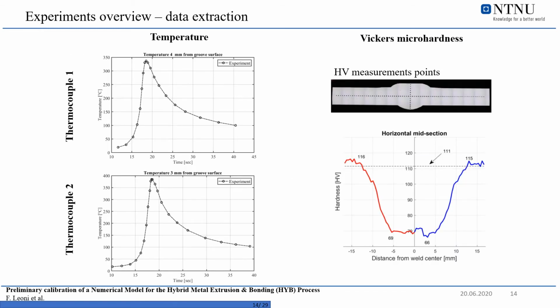Once the weld was run, we obtained the temperature evolution, and as you can see here on the left, of course, 3 millimeters far from the groove surface wall, the temperature is higher since it's closer to the heat source, and moreover, the hardness was measured along a cross section of the weld in order to determine how the temperature field affected the strength of the aluminum alloy.